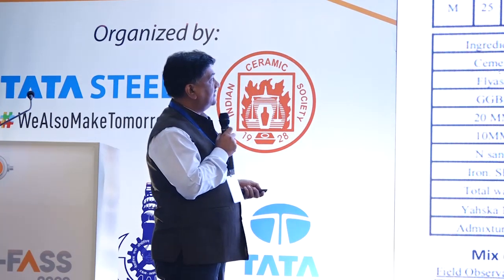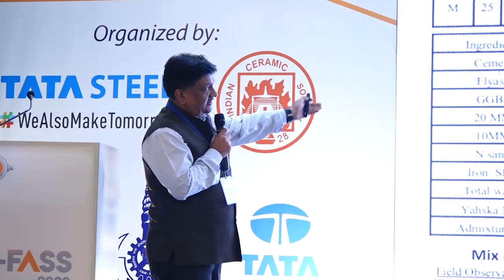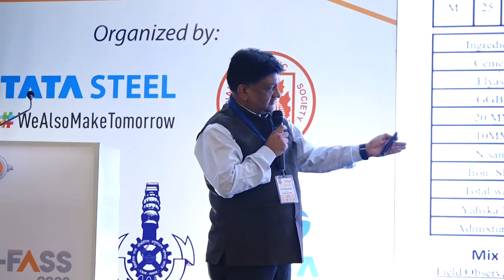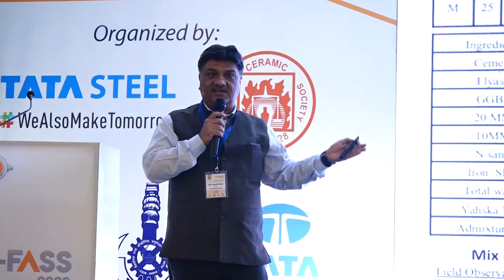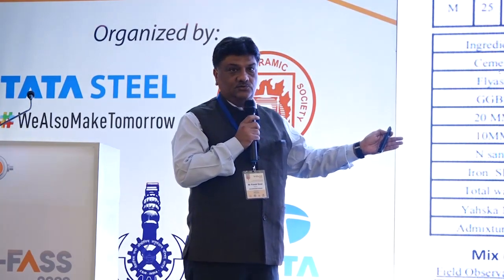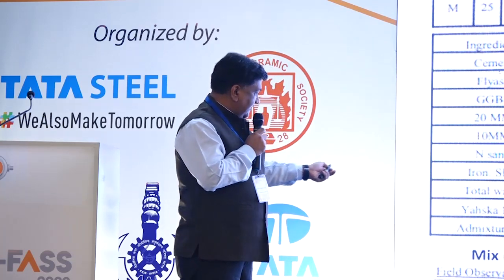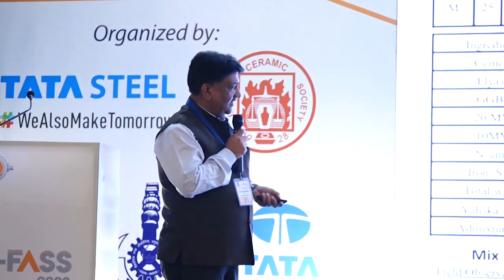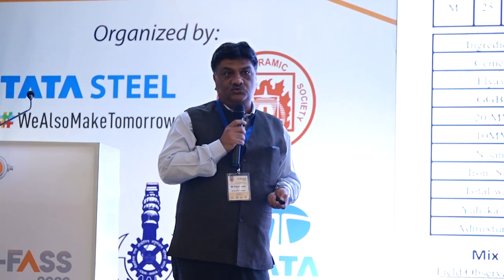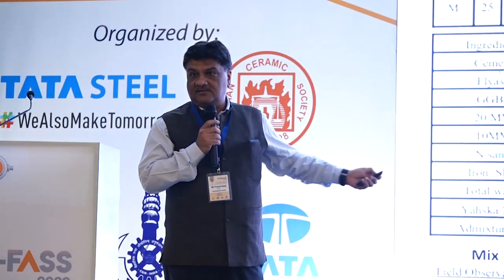So we've done this in Surat at a ready-mix concrete plant near Hajira. You can see the mix design, and the compressive strength behavior right from the first day to 28 days. For M25 grade concrete, considering FCK, the characteristic strength of the concrete, we are surpassing that, beyond 29 MPa. So that's what we got while using the ACBF slag aggregate. Also the workability parameter, the slump, is around 110 mm at 150 minutes. A ready-mix supplier has to keep concrete returnable up to 2.5 hours, which is fulfilled by this approach.